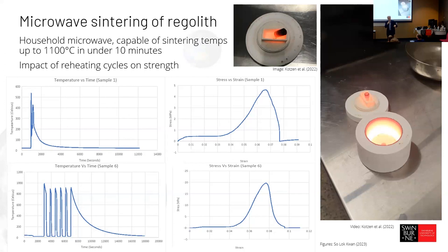So this is something I've been busy with. He came up with this heating cycle with a microwave, and he also measured the temperature. He's found a good way of measuring the temperature. And you can see from the left down to the bottom, he's increased the peak strength by a factor of about 4 or 5, just by applying some simple principles of longer duration and trying to control the cooling. So we're going to get clever and clever at this, right? We're going to keep pushing that up. This is just the start. So we're quite excited by that.